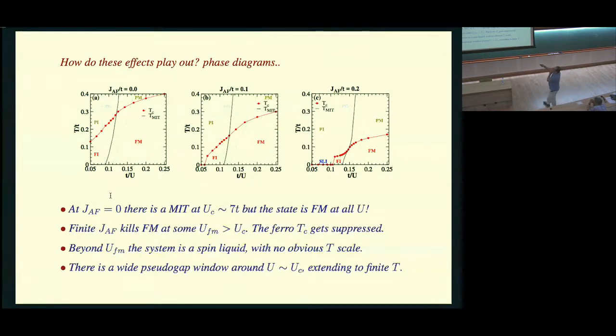So if you don't have any JAF at all, there is no competing antiferromagnetism. Everything is ferromagnetic. You had a ferro-insulator to a ferro-metal transition. To their surprise, the moment you put in a JAF and increase its value, the left-hand side, corresponding to small t or large U, begins to become a spin liquid insulator. I don't get a spin glass because there is no extrinsic disorder in the problem. If you had put weak extrinsic disorder, this probably would have frozen into a glassy state. But within the scenario I'm working, I don't seem to see any freezing transition at all on cooling down the system. But spin disordered and orbital disordered in this neighborhood, and that seems to have a dramatic effect on the transport properties that we observe.